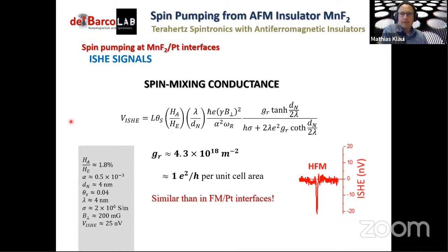That is maybe one way of going, because definitively we don't think that the electric signal that we observe beyond the spin flop transition relates to circularly polarized modes of the antiferromagnet. And most likely, it cannot come from linearly polarized modes either, so it has to come from a different kind of magnon modes. But it's something that we're trying to explore. These are not easy experiments, but there's a way to try to study this along the lines that you're suggesting.